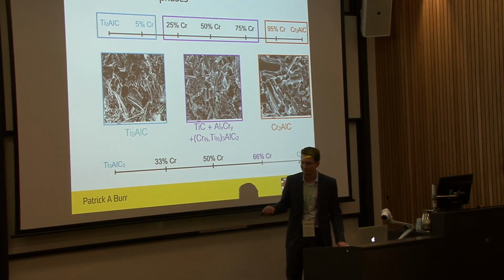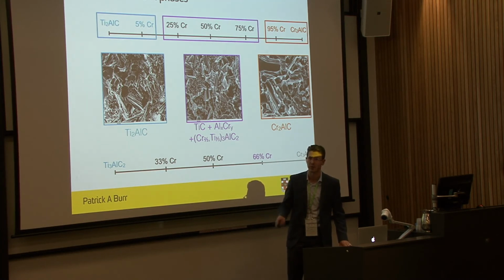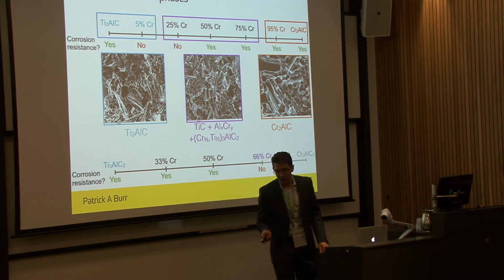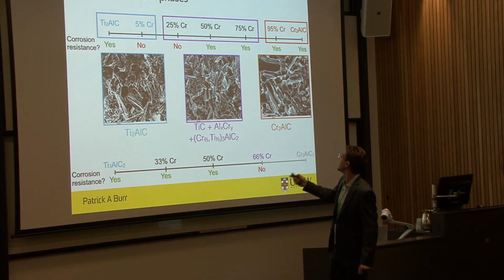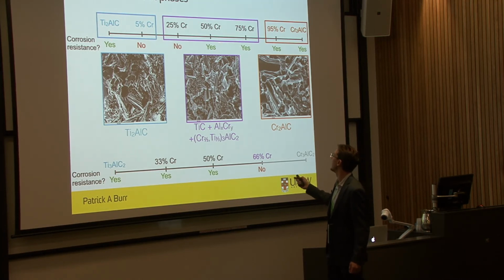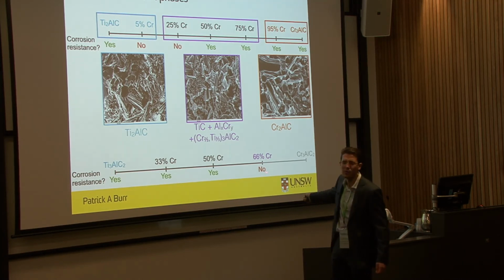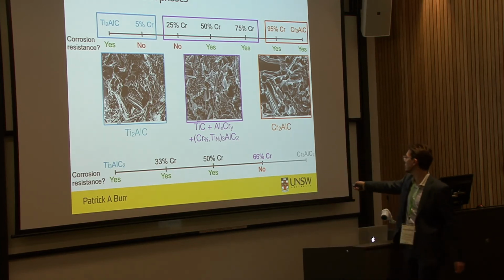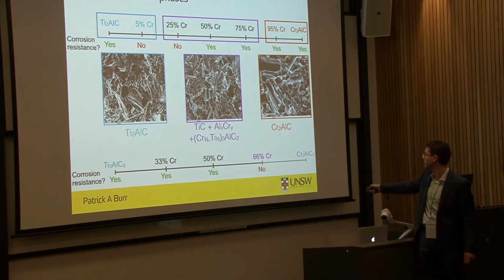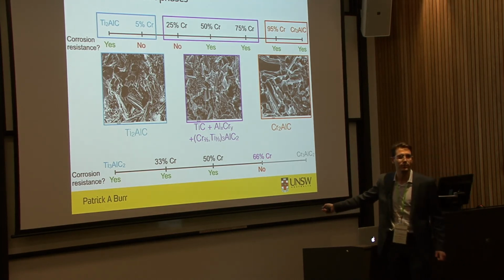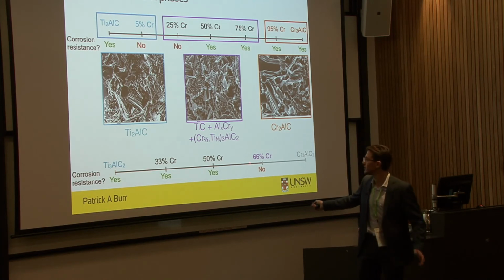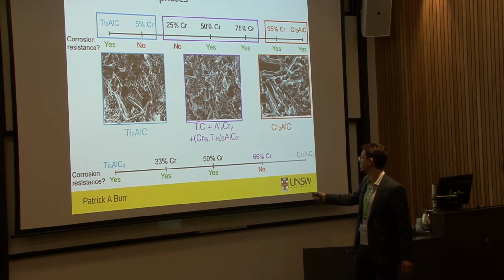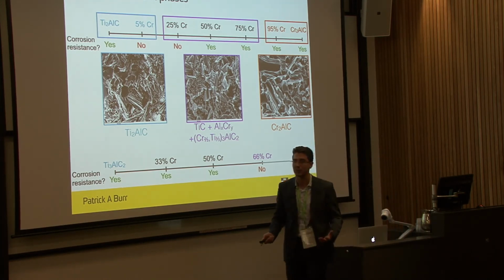Nevertheless, we looked at the corrosion properties of this. We tried to oxidize them. And what's interesting is that the parent MAX phases, we know they have very good corrosion resistance. Interestingly, this one, I must say, has terrible oxidation resistance. The new phase that we formed, the 2/3, 1/3 chromium, titanium, aluminum carbide, it just disintegrated in air. It's absolutely dreadful. Though it's very interesting, I've got a couple of publications on why this forms, which is very interesting from a materials point of view.